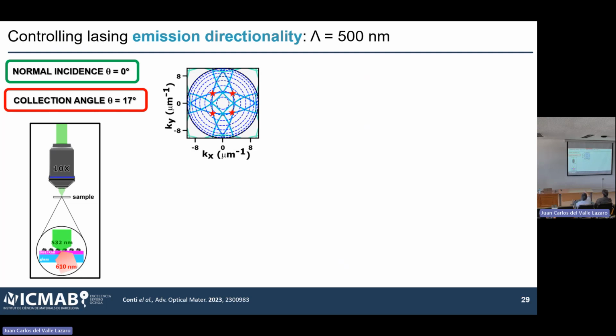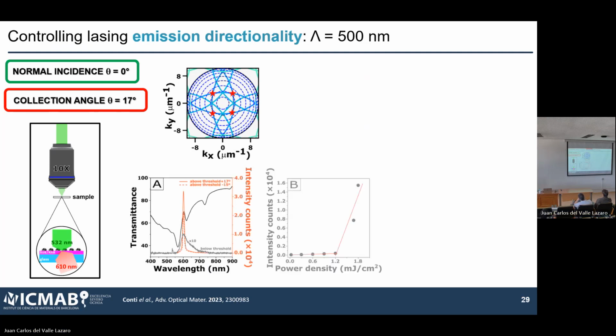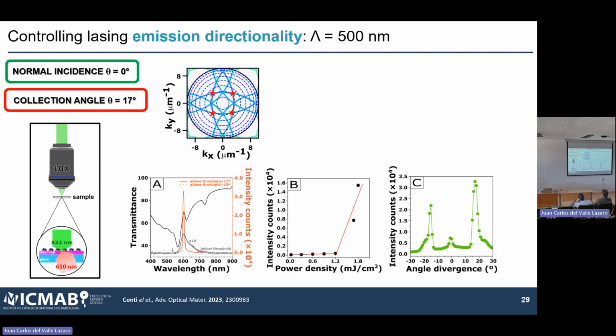And so what angle? Well, every concentric circle that you see here is 10 degrees from the center, which is normal emission. And so we should expect it around 20 degrees, let's say. And this is what we observed. This is our emission at, let's say, 17 degrees, but very close to 20 degrees. So here is the angular dependence, and this is the threshold behavior. In this case, though, the threshold is much higher, almost 4 times higher.